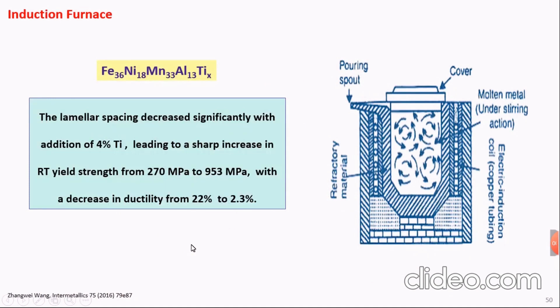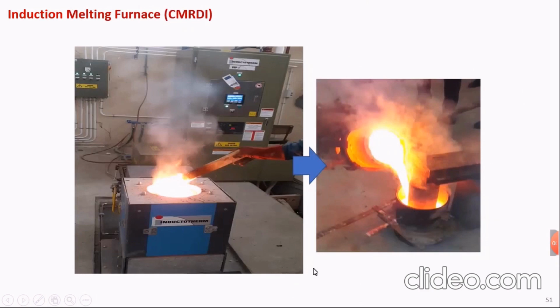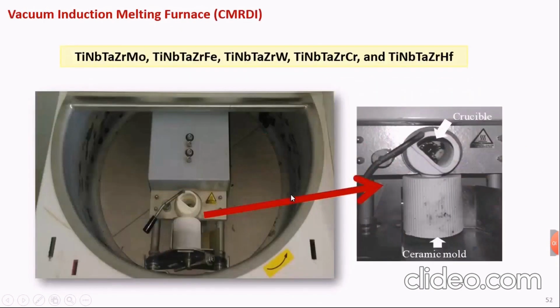The second important melting method is induction furnace, induction melting. In this method, the charge is inserted into the crucible and surrounded by an induction coil, and this method is suitable for melting most high entropy alloys, except for the refractory ones, which require much higher temperatures. At my institute, we have two facilities. We have an induction melting facility in open air, and there we use non-reactive high entropy systems. For reactive high entropy systems like titanium biomedical high entropy alloys, we use a vacuum induction melting furnace to avoid oxidation.